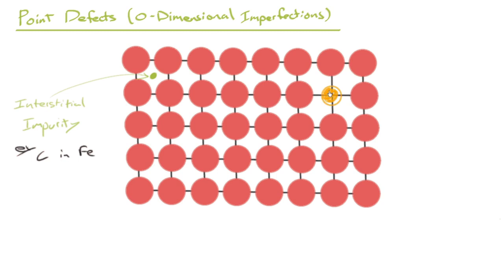We could color it in like this. I happened to draw one that was a little bit smaller than the impurity atom. But that would still be an impurity. But it's not in an interstitial site this time. It's now substituting. So we call that substitutional impurity. And that happens again. To go substitutional, they have to be about the same size, usually within about 10%, same size, same crystal structure, similar electronegativity so they don't react and form an ionic compound, for example.